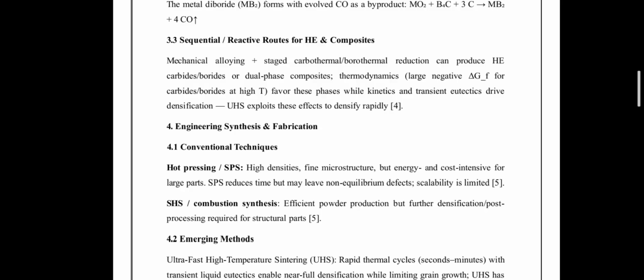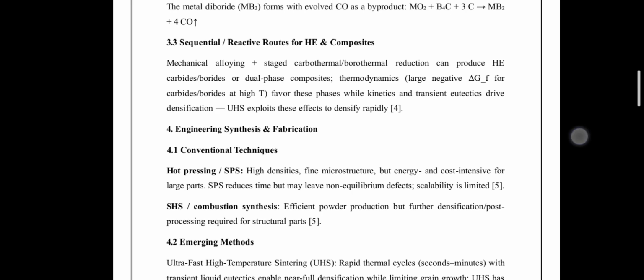Second is combustion synthesis. Self-propagating high temperature synthesis, or SHS, is an efficient route for producing ultra high temperature ceramic powders through highly exothermic reactions. While SHS offers low external energy input and rapid synthesis, the resulting products are typically porous and inhomogeneous, and require subsequent densification steps such as hot pressing or SPS for structural applications.